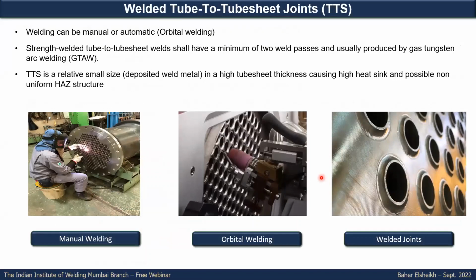Now we'll come to whenever we are applying welding for the tube-to-tube sheet joint. Welding can be either manual or automatic, by orbital welding techniques, and usually applied with gas tungsten arc welding. It is highly recommended to have a minimum of 2 weld passes. This recommendation you will find in many standards, including API 660. 2 weld passes as a minimum, and might be more. So also, in the selection of the filler wire, you have to respect achieving this during the qualification of the WPS.